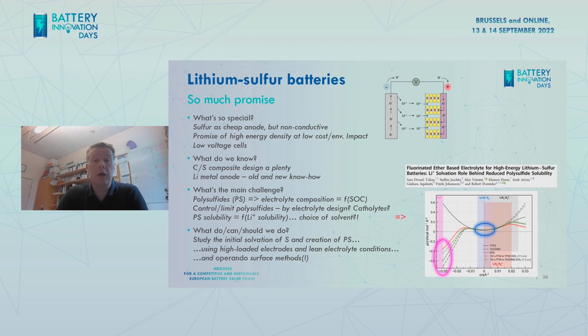And it's important to realize the polysulfide solubility is actually a function of the lithium salt solubility. That is something that we're doing a little bit of modeling on, where one can see that if you have, for instance, a fluorinated solvent, people say, yeah, but that limits the polysulfide solubility. Yes, but it does so by the fact that it doesn't solubilize the lithium cations. So if you link those two together, the choice of solvent becomes rather tricky, because you want lithium salt present, of course, because that's going to be a charge carrier of interest. At the same time, it tells you that you're going to have some polysulfide solubility. So more complex electrolytes than perhaps have been studied so far.